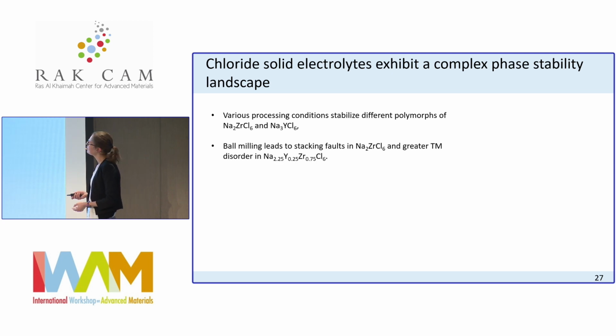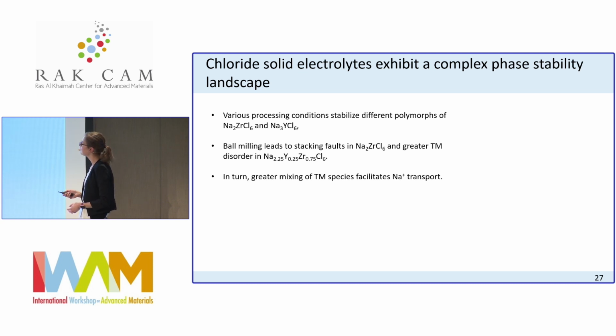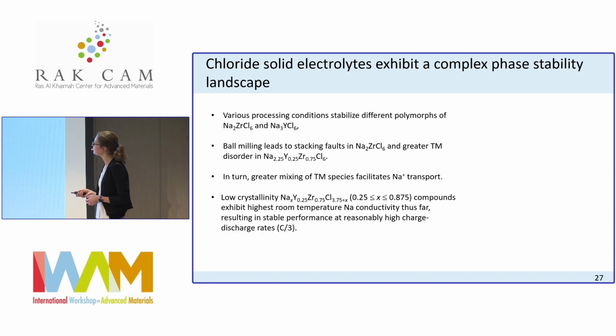So just to recap here, what have we learned? We've learned that in these materials, the processing condition is very important because it will allow you to control the polymorphs that you form. And we've seen this with NZC and NYC. We also see that ball milling will lead to stacking faults in some of these polymorphs. It increases transition metal disorder in the mixed transition metal system. And in turn, this greater mixing of transition metal species facilitates sodium transport. In the low crystallinity sodium deficient compounds, we can see that now we have a high room temperature sodium conductivity.